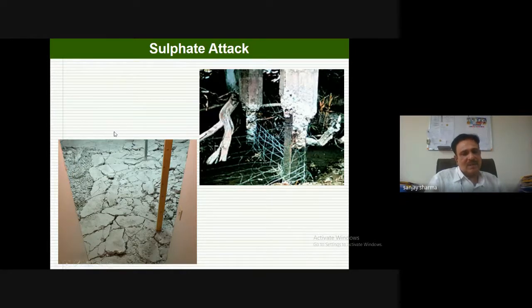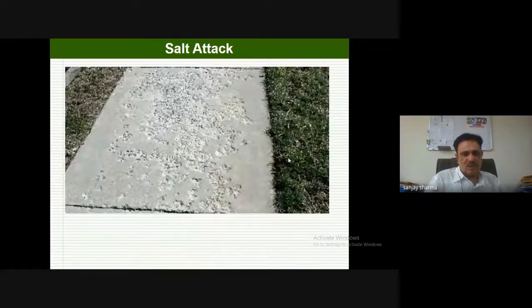And then maybe the quality of the water used was also a factor, because we tested the sulfates by taking samples. The sulfates in one tank were more, and in the other tank, which was in good condition, the sulfate was within reasonable limits. So a lot of factors contribute, and that is what we have to find out by using these techniques.